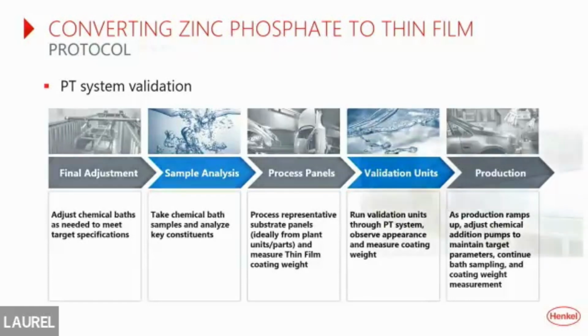And then your customer's going to run validation units and measure the coating weight. Another nice thing in today's world, we can use X-ray fluorescence or an XRF unit to measure the coating weight right at the customer. For those of you who have not seen it, you can get a handheld unit that looks like a police radar gun. You can stop the car, put it right up there. 30 seconds later, you have a coating weight as opposed to taking it to a lab and doing a weigh-strip-weigh on it. So it's very convenient.